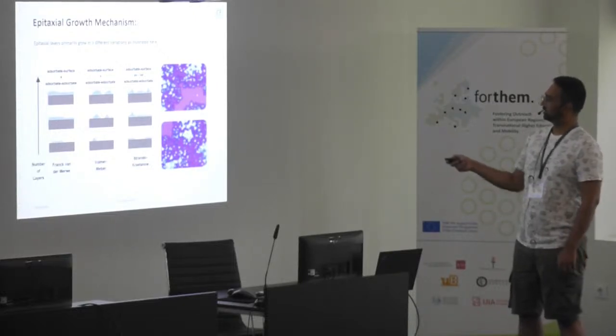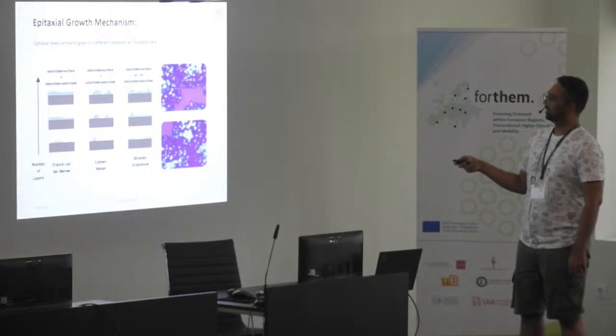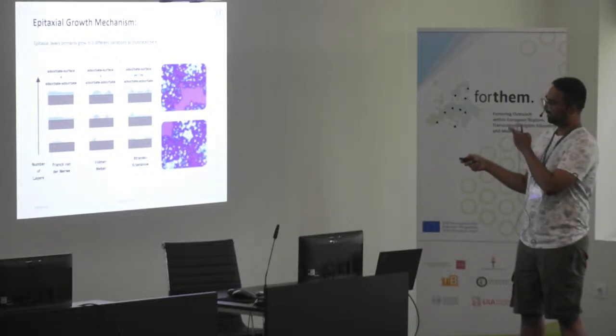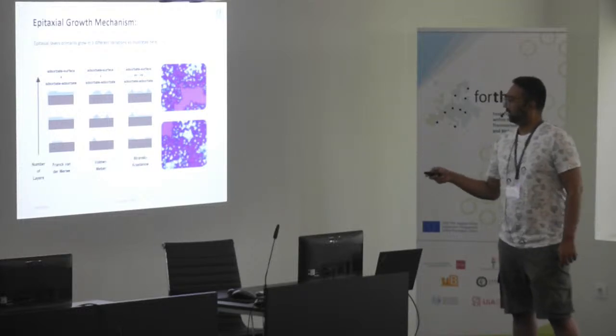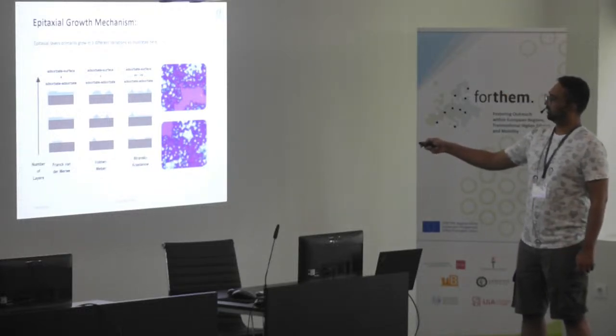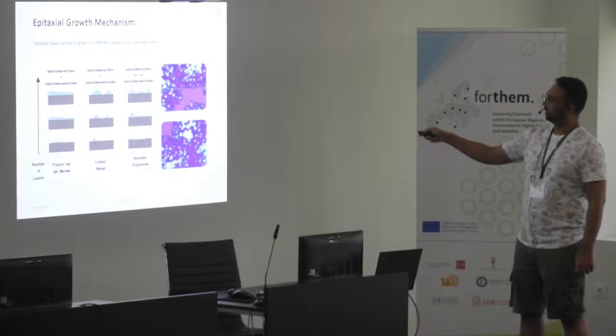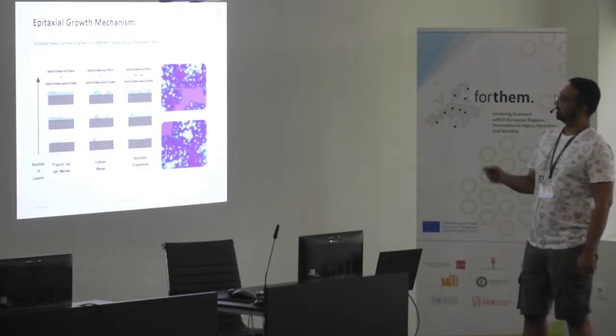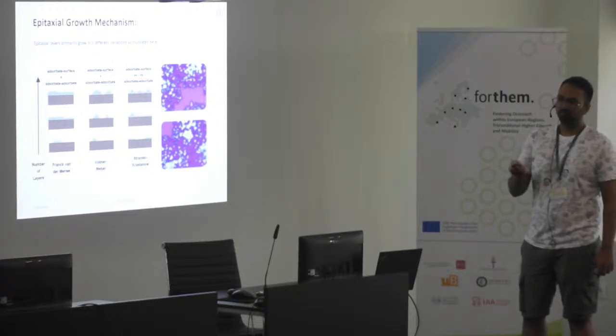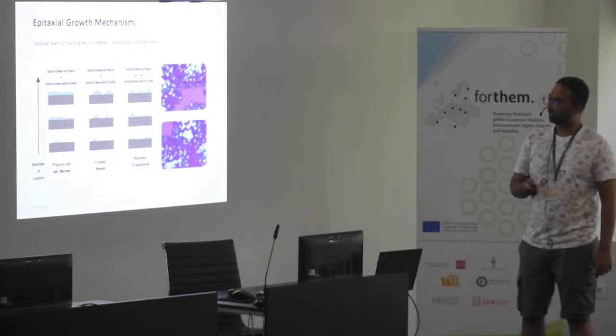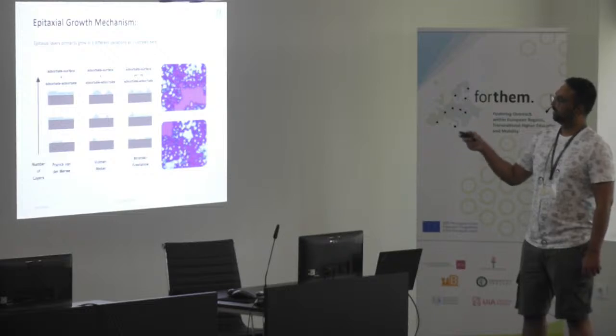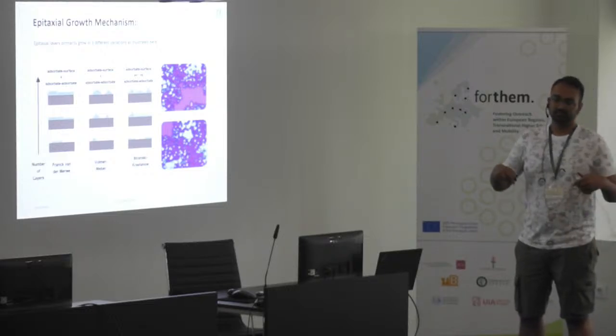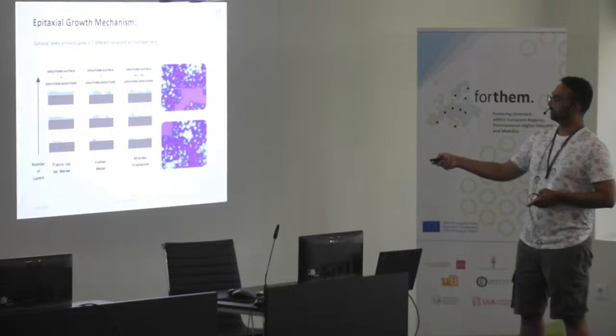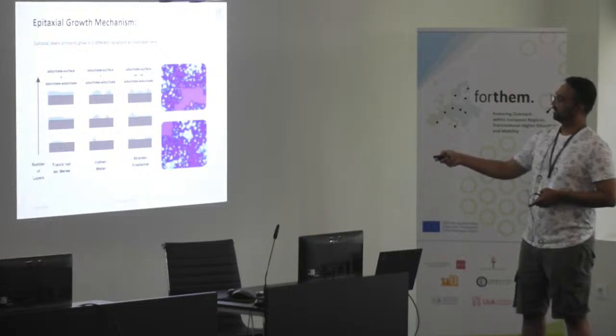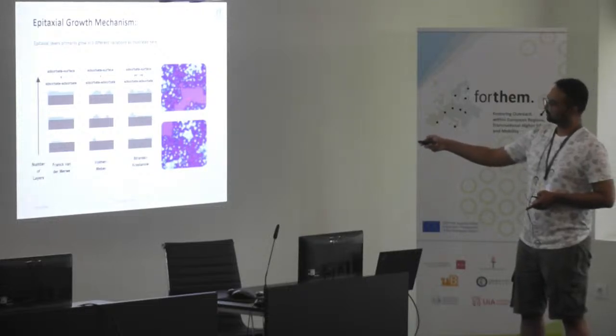And here you can see some actual images of tungsten diselenide on the silicon oxide substrate. The pink part is the oxide where there is nothing, but the purple area is where the monolayer of tungsten diselenide is. It grows and then it prefers to grow on itself. That's why it starts to make this triangle on itself, and it doesn't prefer to grow outside.